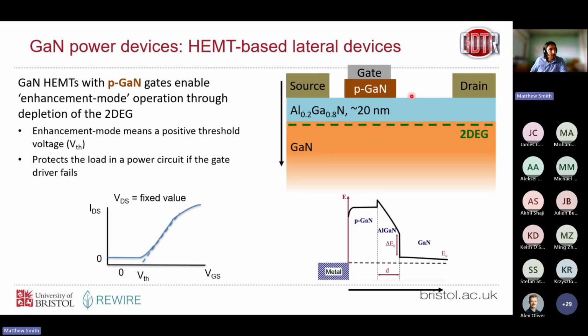So what people did was introduce this p-type GaN layer underneath the gate. So it's a very similar structure, the GaN power device, lateral GaN power devices, but we're able to achieve this enhancement mode operation where now our threshold voltage is greater than 0. So now if our gate fails, the device is off, and actually we have to apply a gate voltage to turn the device on. That's achieved by this p-GaN layer, which depletes the 2-DEG through a PN junction here. So actually when we apply a gate bias, we put the gate into forward bias, we reduce our depletion region, and the device turns on. So very similar to the HEMT structure, but just with this additional layer here, this p-GaN layer. And we can see at 0 volts, it's raised the conduction band above the Fermi level, so it's normally off, protects the load if the gate driver fails.